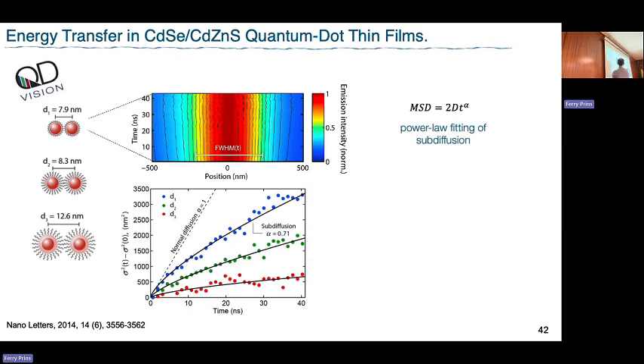Then we can quantify this for all three: how fast does my population broaden as a function of time? I have my short distance and longer distance cases. You can see that it's clearly slower when I space my particles out further, which makes sense because Förster transfer is very sensitive to the distance between particles.